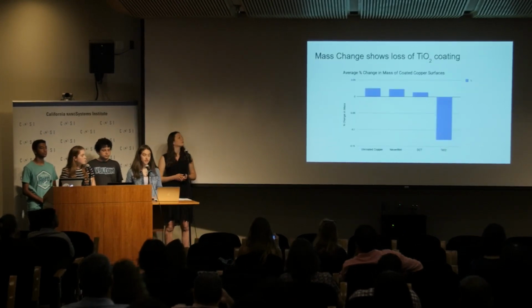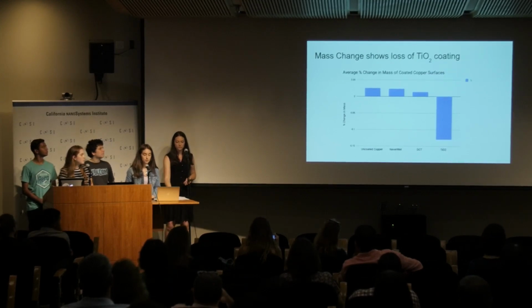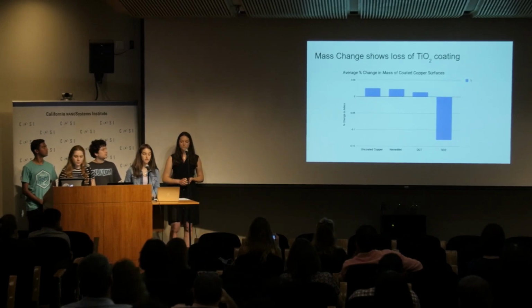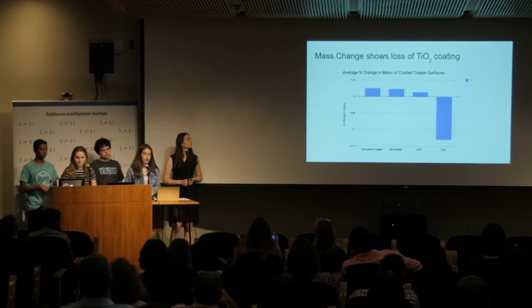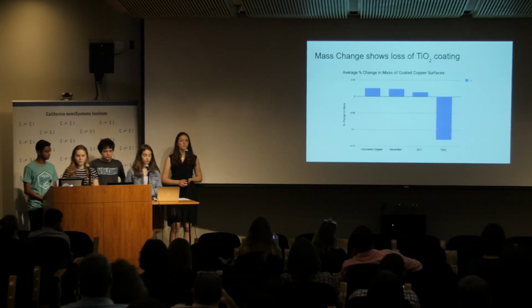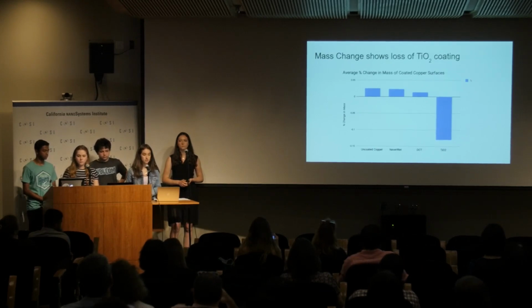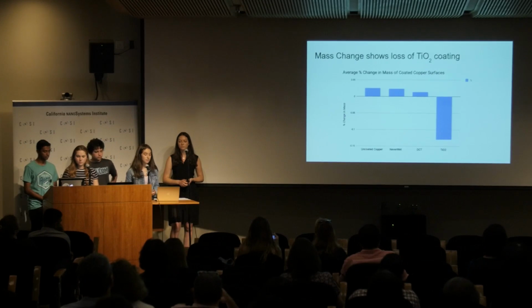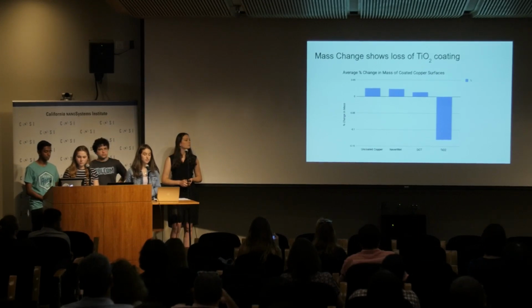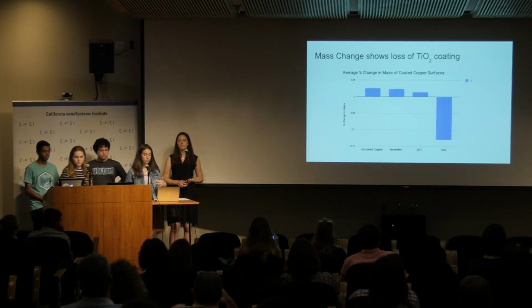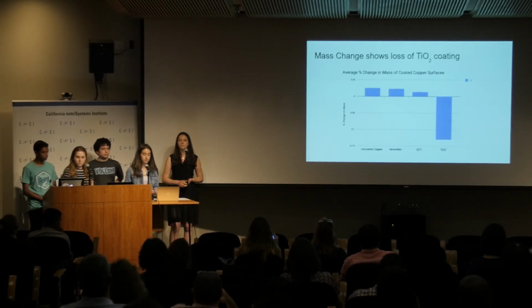So after calculating the percent change in mass for each copper sample, we found that the difference between the final and initial masses of the copper pieces were not significant enough to indicate corrosion. However, the uncoated copper, the Never Wet, and DCT coated samples had a very slight increase in mass, while the TiO2 copper had a decrease in mass. And we think that this happened because when the TiO2 copper pieces sat in the pH solutions overnight, the TiO2 film on top of them degraded, therefore accounting for the decrease in mass.